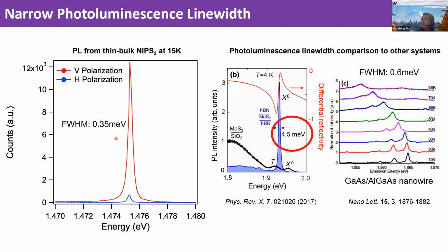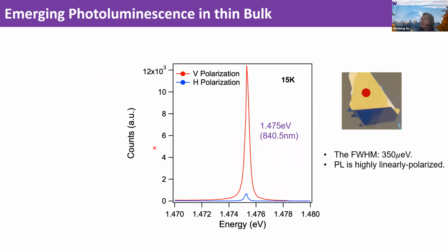The second thing that caught our attention is the very strong anisotropy of the system. In this spectrum, you see two curves, one red and the other blue. We performed linear polarization resolved measurements. The red means that the polarization is along V, which is along the b axis, orthogonal to the zigzag chain, and H is along the zigzag chain. So you can see that the luminescence is strongly polarized in this vertical direction.